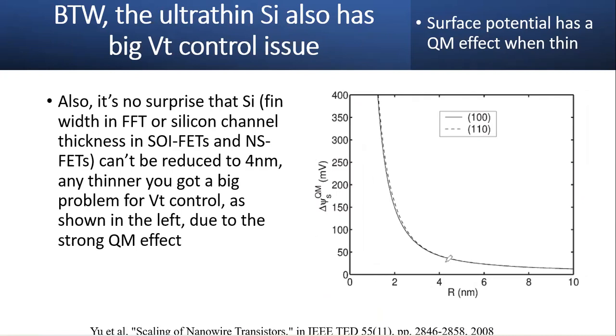If you look at the graph on the right hand side, this is for the nanowire, pretty similar for the thin film as well. You can see that the surface potential has a strong quantum mechanical effect. So when you go down to below 4 nanometer, your surface potential shoots up, and you cannot work in this region, right?